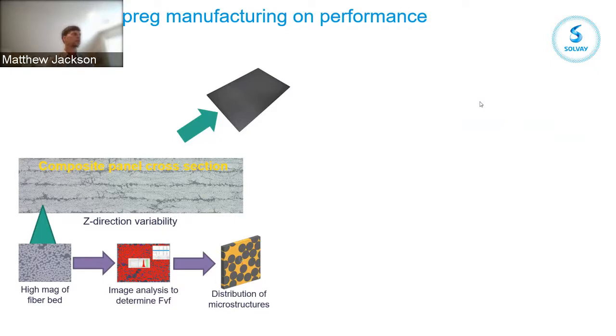And so if we take this composite panel, which you see on the top, and we do a side view, again, we're bringing back our polished cross-section, where the little white dots are the individual fiber filaments, and the dark areas are the resin. We can zoom into that area, and we can start to understand the variability. And so depending on both the prepreg manufacturing and the composite manufacturing, we can get some variability in our microstructure. And that variability leads to changes in performance. And so best case scenario is a completely consistent homogeneous material. But again, that's sometimes hard to achieve.